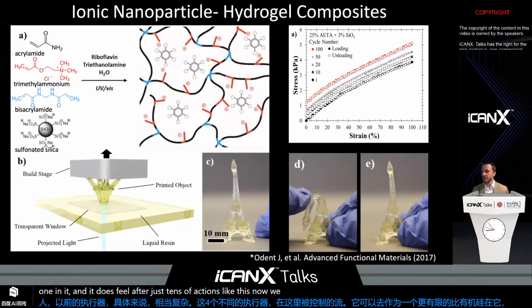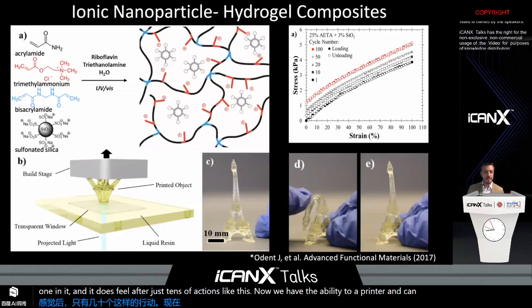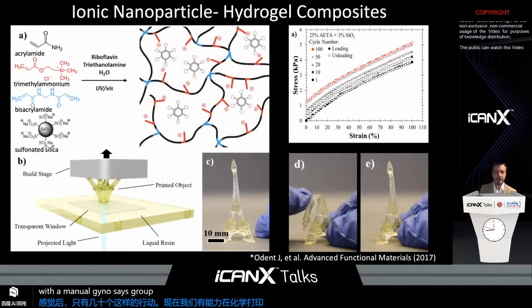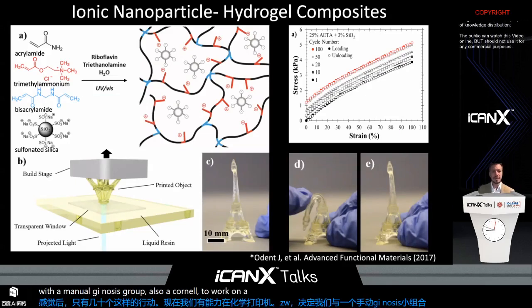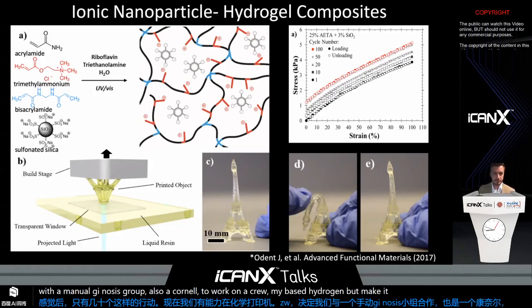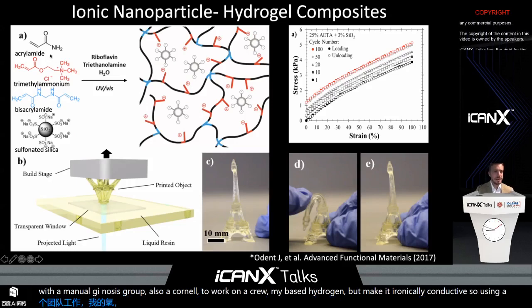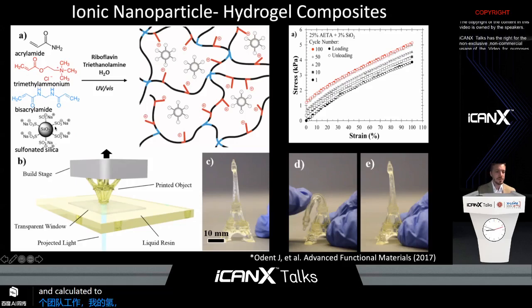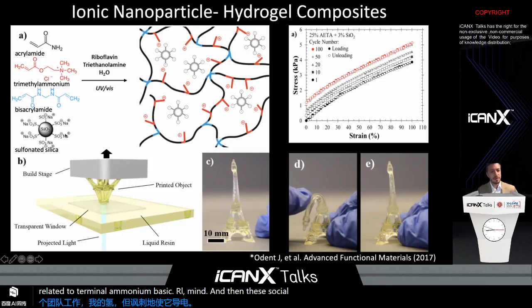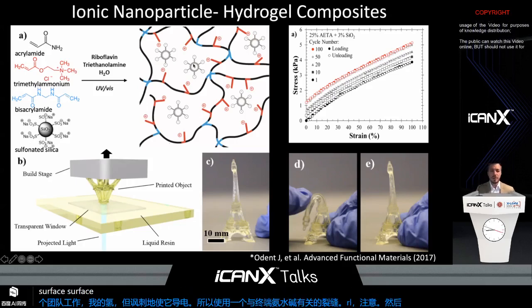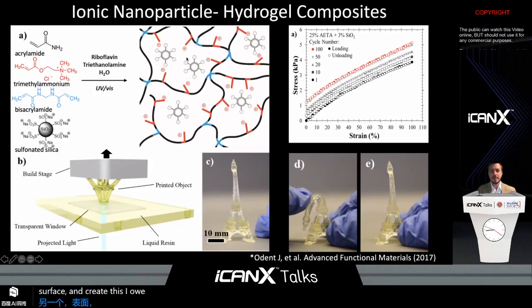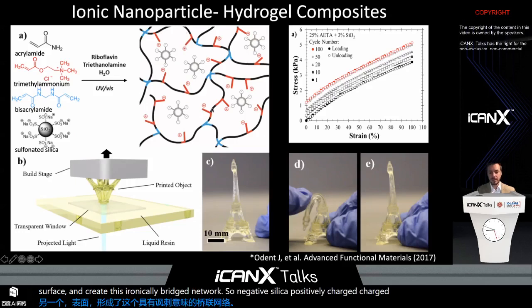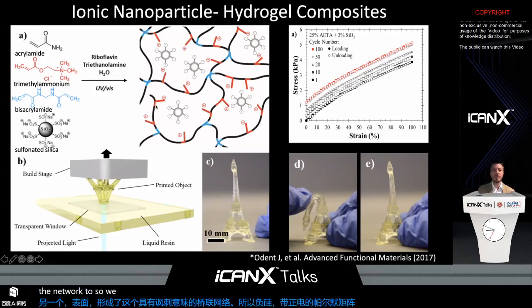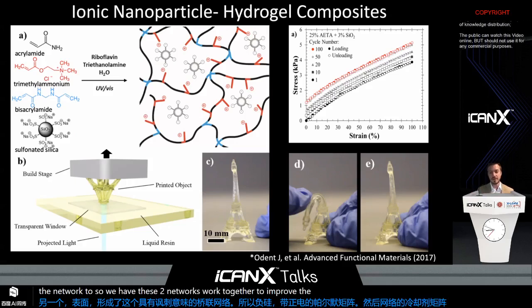Now that we have the ability to print our own chemistries, we worked with Emmanuel Giannelis's group, also at Cornell, to work on an acrylamide-based hydrogel, but make it ionically conductive. So using acrylamide, an acrylated trimethylammonium bisacrylamide, and then these sulfonated silica particles, negatively charged, tethered to the surface, we can create this ionically bridged network. So negative silica, positively charged polymer matrix, and then the covalent matrix of the network too. So we have these 2 networks working together to improve the toughness of these hydrogels.